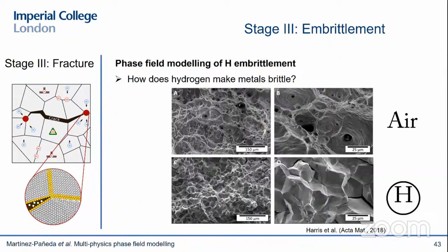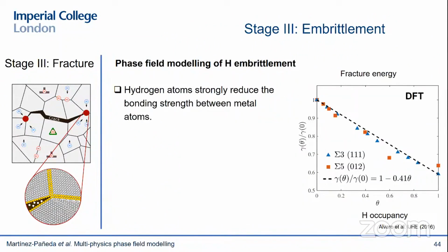So if you think of it first from an atomistic perspective, what you learn from atomistic calculations is that hydrogen very significantly degrades the bonding strength between metal atoms. You can see here, these are DFT calculations for multiple grain boundaries in nickel. And you can see that if your grain boundary is full of hydrogen, a coverage of 1, then you get a 40% reduction in your surface energy or fracture energy. So hydrogen is going to make that grain boundary weaker. And then the question is, of course, how much hydrogen do we have in our grain boundary? Because if it's very little hydrogen in my grain boundary, then there must be another mechanism taking place. So where are we on this x-axis?